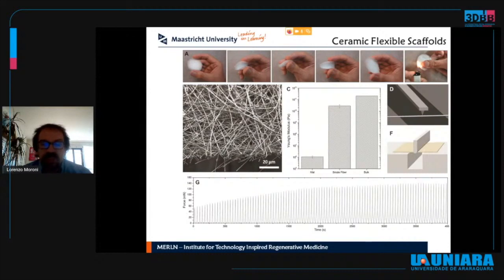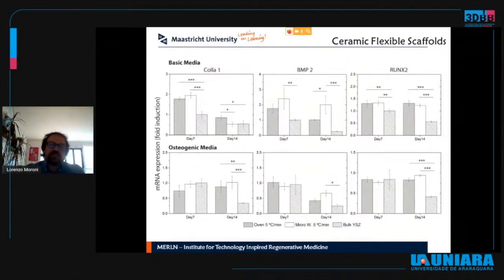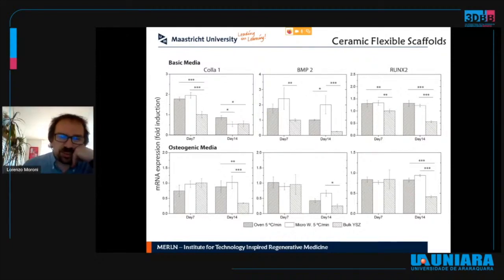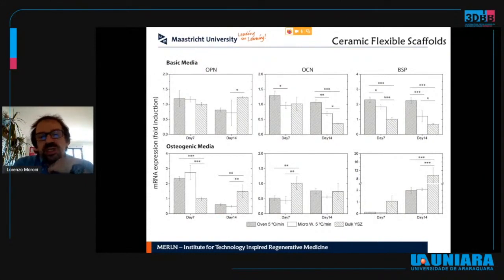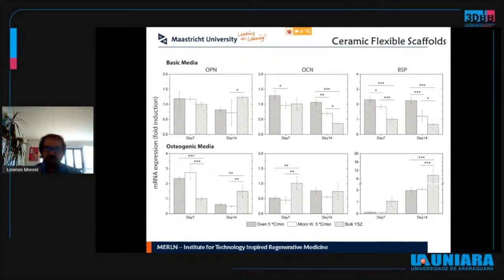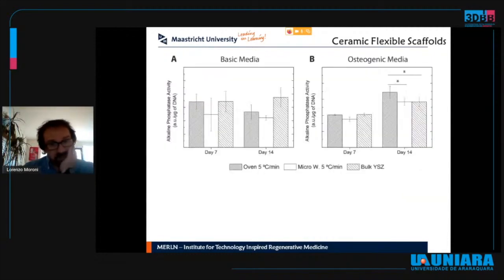You can see that whereas at the single fiber level the stiffness of the material is the same as the bulk stiffness of a disc of zirconia, at the mat level, at the scaffold level, the mesh is much more flexible. This was also coupled to fatigue tests, where these scaffolds were able to sustain cyclic loading up to more than 4,000 cycles. We then cultured adult bone marrow-derived stem cells on these scaffolds and, interestingly, found that already in basic media there was an increase in gene expression of a set of both early and late osteogenic gene markers, especially for the scaffolds sintered at a lower speed, in an oven at 5 Celsius per minute, which were the scaffolds with the highest nano roughness on their surface.